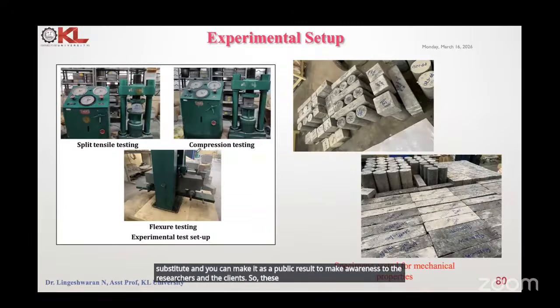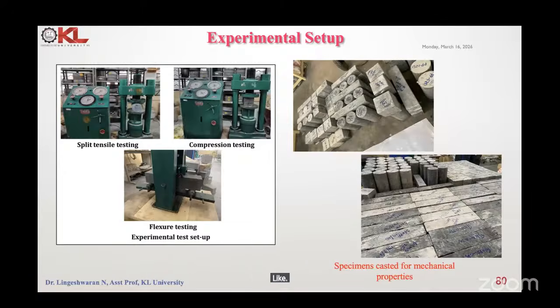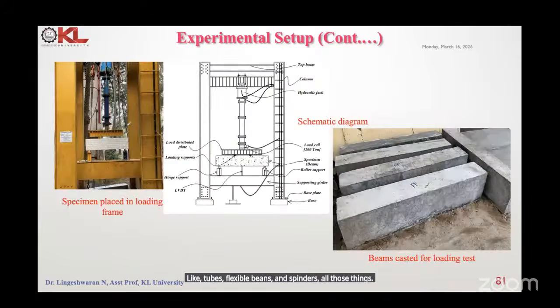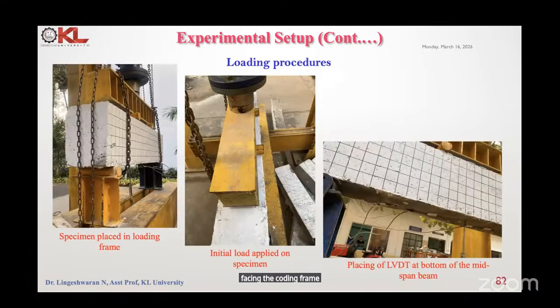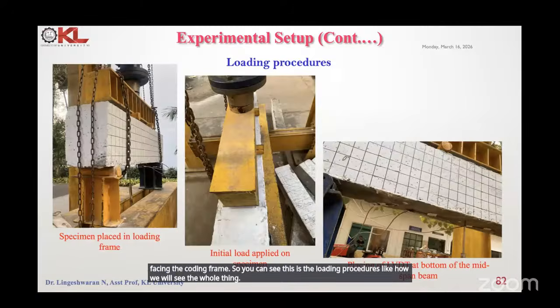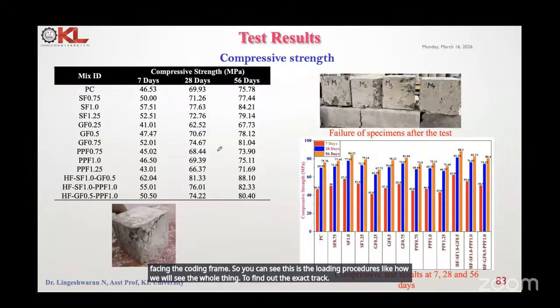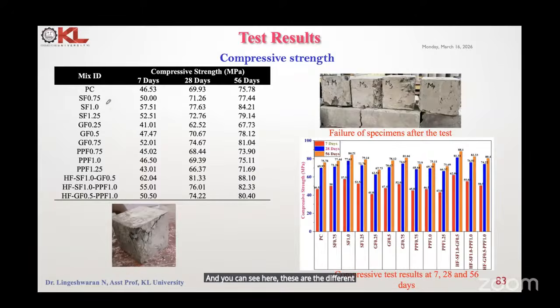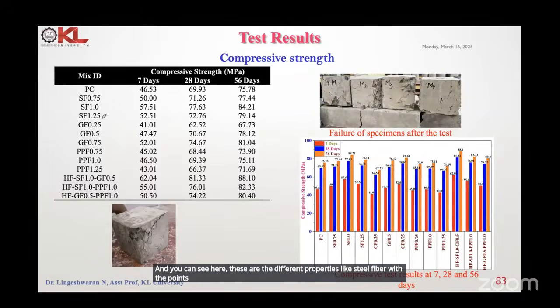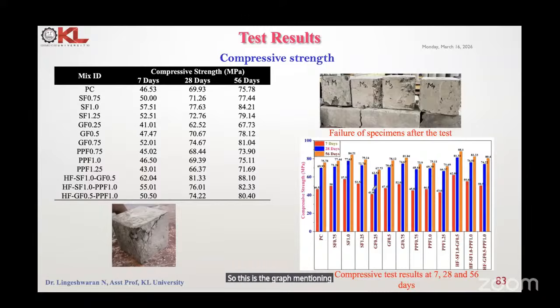These are the different mechanical properties we tested, like cubes, flexural beams, and cylinders. You can see this is the test specimen of the beam. Then the beam is cast for placing in the loading frame. This is the loading procedure, like how we keep everything. An LVDT is used to find the exact crack width in mm. And you can see the different mixes like steel fiber at 0.75, 1, and 1.25%, glass fiber, polypropylene fiber, and hybrid fibers. These are the compressive strength tests from 7 days to 28 days to 56 days. This graph shows the compressive test results.